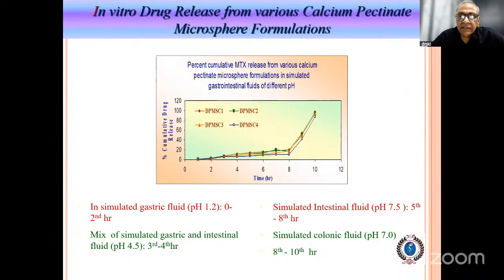Right. So when these microspheres come in contact with the simulated colonic fluid, there is a digestion of the calcium pectinate and release of that drug. So we observe a high amount of that drug after 8 hours.